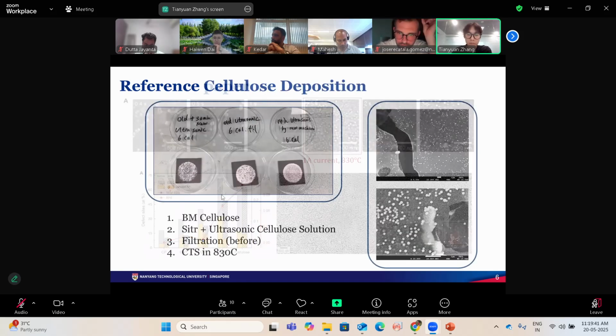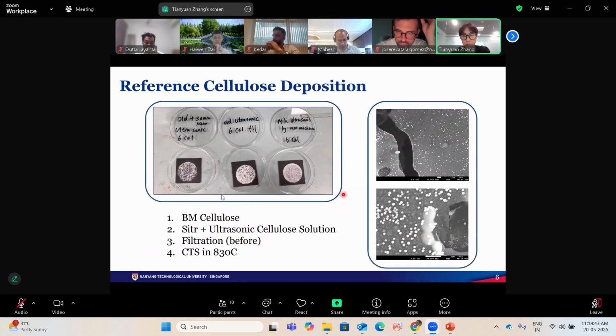Based on this background, we started our experiment, following the method mentioned in this reference paper. We used ball milled cellulose and applied stirring and ultrasonication to make our cellulose solution. And we changed a lot of different parameters.